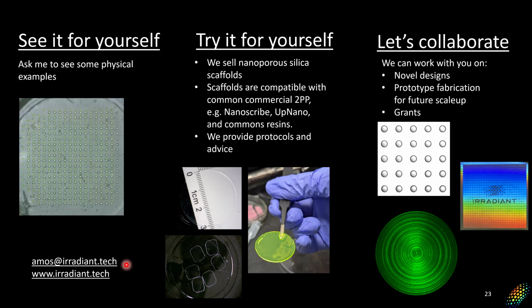So, how do you envision mounting your components in a free space environment? There are a lot of different ways you can think about doing that, depending on the needs. The most simple, brute force solution is you can just directly epoxy or glue these onto structures. I mentioned quickly, you can machine them or laser cut them, so you can cut them to certain shapes and slot them into things. We've also been able to use the polymerization process in lithography to tack them down onto a surface. You can functionalize a glass surface and then polymerize and attach down onto that during that step.